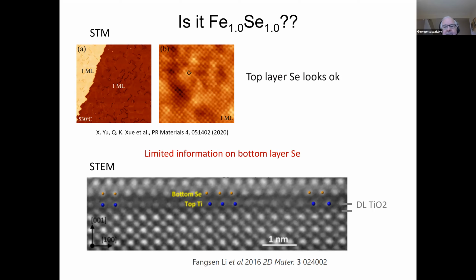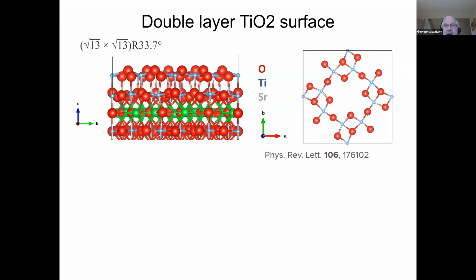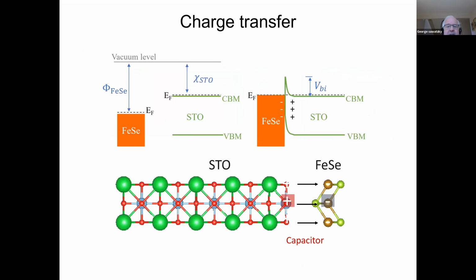Okay, so we tried that, but that doesn't really do much to the band structure actually, although it has a very interesting effect. If you do the density functional and LSDA calculation, you find G-type antiferromagnetic order, so not stripy. That doesn't mean that it's not stripy, but the lowest energy is not stripy in this calculation. But you find that the two moments up and down are not equal. So now you have time reversal symmetry breaking. So be careful. You have now a dipole and time reversal symmetry breaking. I wonder if that really happens, but we don't really know. I'm going to skip this part because I'm running way out of time.